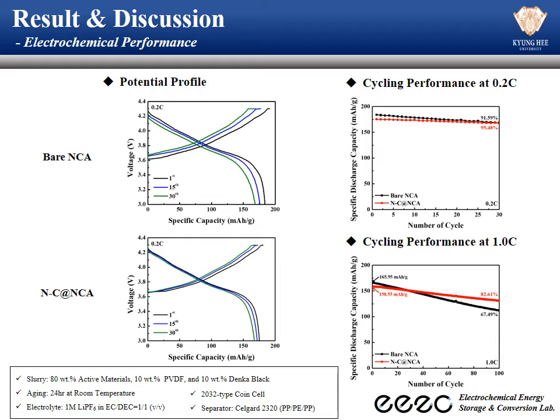Next, in order to confirm the difference in electrochemical performance between bare NCA and N-C@NCA, the active material is mixed with 10% of PVDF as a binder and 10% of Denka Black as a conductive agent, and after mixing them, NMP is added to form a slurry. After that, laminating is performed on the current collector and dried to obtain an electrode. The obtained electrode was assembled in the form of a 2032 type coin cell together with an electrolyte and a separator. And after aging for about 1 day, the electrochemical performance was evaluated.